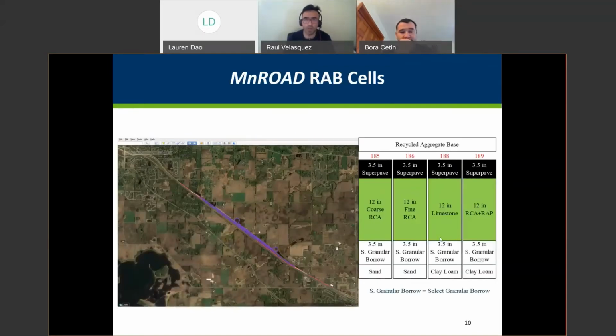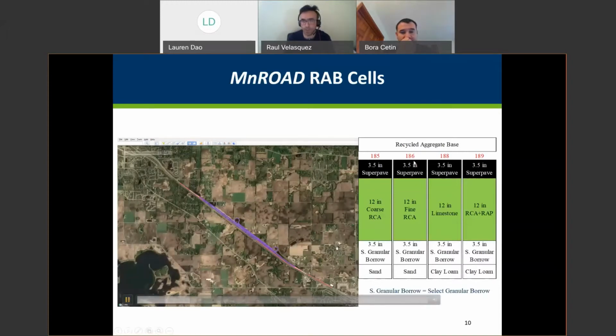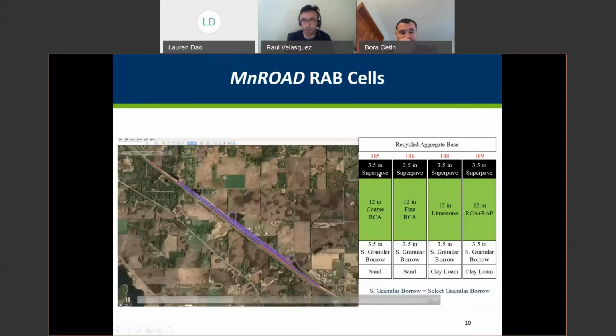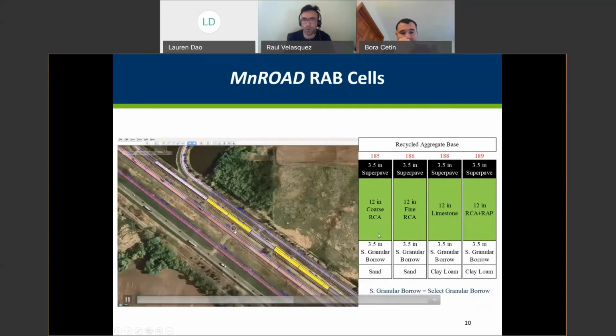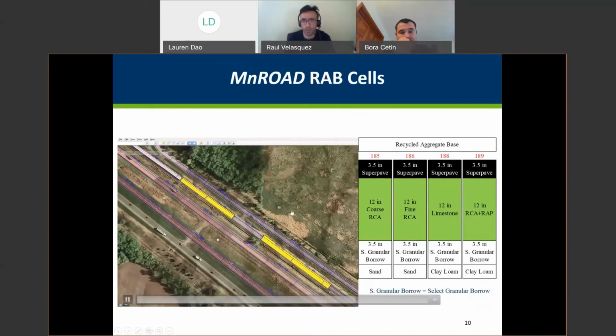So what are the MnROAD recycled aggregate base cells? Our cells are 185, 186, 188, and 189. The cells are located in the low volume road loop on the west side. 185 and 186 are founded on sand subgrade, and 188 and 189 are founded on clay loam subgrade. So keep that in mind. In terms of thicknesses, they're all the same. The top material is the same. It's a 3.5-inch Superpave mix design, 12.5 maximum aggregate size mix.